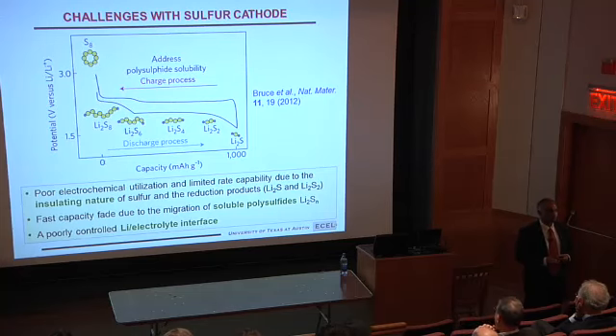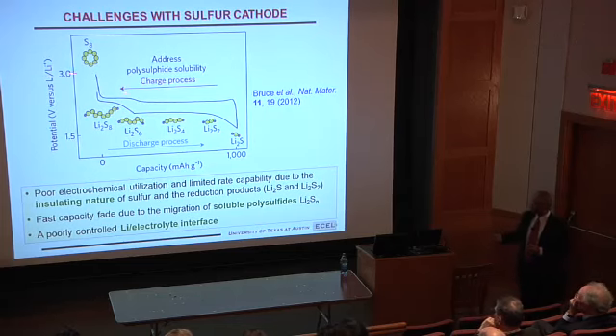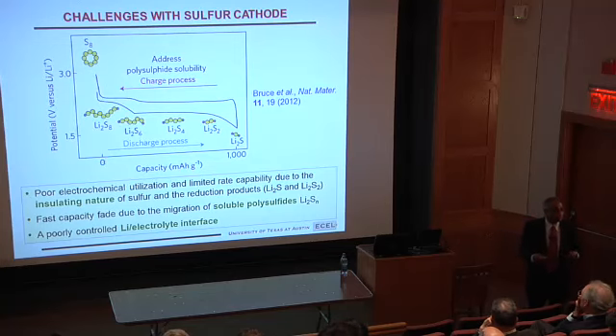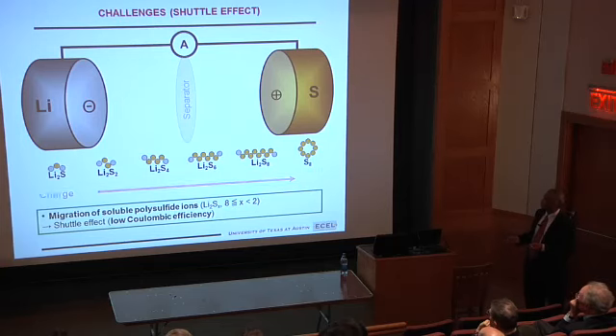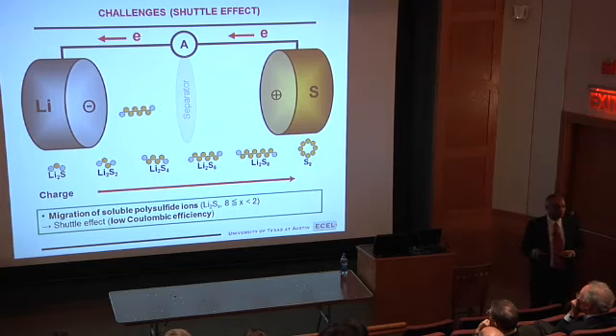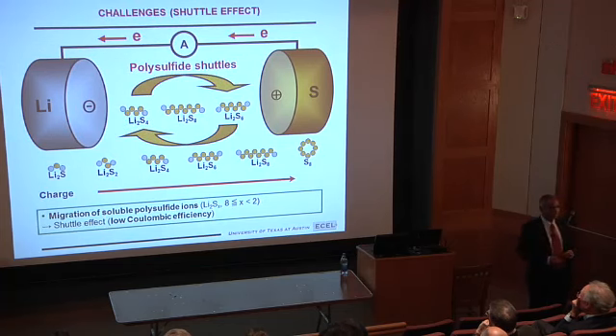How does it compare with lithium sulfide, for example? Lithium chloride will be much more insulating than this. So two problems. Insulating, so you have to have some conductive agents. These dissolve, so when they dissolve, they migrate from here to there. That causes a Coulombic efficiency problem because you are losing the active material. It also goes and deposits on the surface, and that gives you bad lithium anode performance.